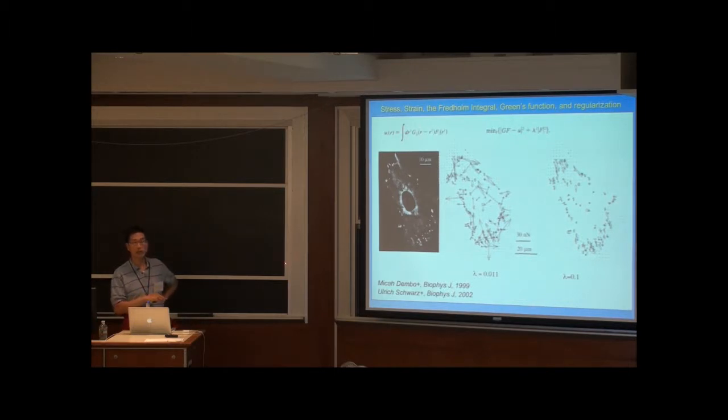Okay, and for linear materials that have a half space and you're trying to deform it on the top surface, there's a solution to what the Green's function is. And so given that that's already known, then it's fairly easy to take a stress field, apply the Green's function, integrate it, and then give you the strain fields. It's very easy to go in this forward direction.